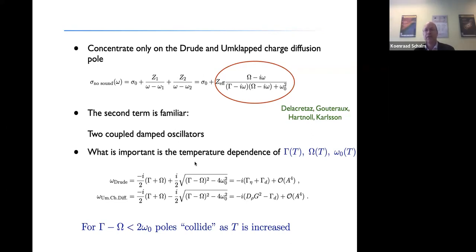What is different compared to the decaying charge density waves in the system is that now the temperature dependence in this Umklapp hydrodynamics is different. The temperature dependence of these effective coefficients, capital Gamma, capital Omega, and the interaction strength, omega naught, is different from that in the modulated wave, and we can compute it here. And then you see that in this particular case, what happens is that the poles collide as temperature is increased.